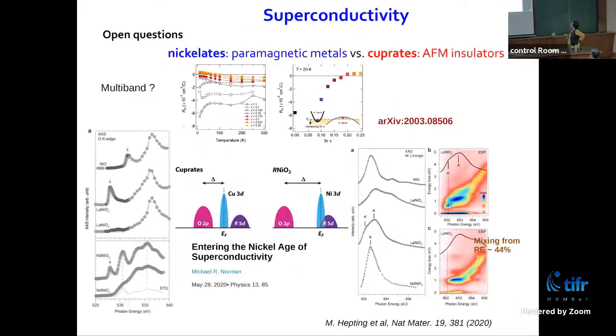Well, since then there have been, I think, many open questions and also a lot of debate. Are the nickelates the same as cuprates? The first striking difference, even at the undoped stage: undoped nickelate is a paramagnetic metal, a bad metal, as opposed to cuprates, which are antiferromagnetic insulators. That means their magnetic exchange scales are very different.